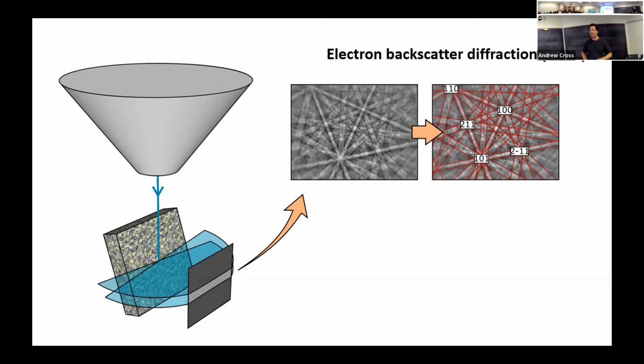And those cones are going to intersect a phosphor screen. This is our detector here. As the electrons hit the phosphor screen, it'll luminesce, and we can capture that luminescence with a camera situated all the way back here. So this is just a reflector for one particular crystal plane, but we've got crystal planes in all sorts of directions. So we end up with a bunch of bright bands that we can then convert, using a special algorithm, into specific crystal lattice planes, and that's based on the crystal structure of a particular mineral.